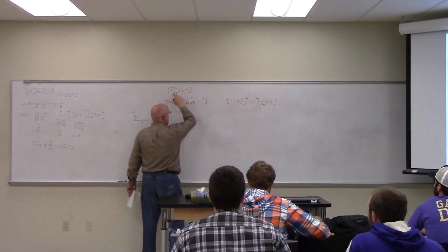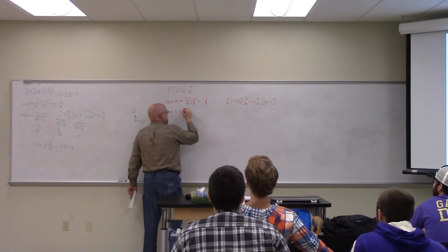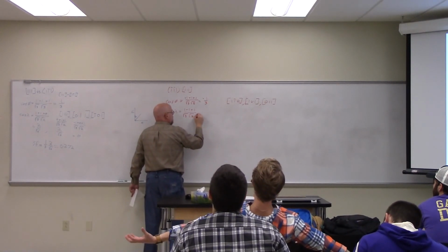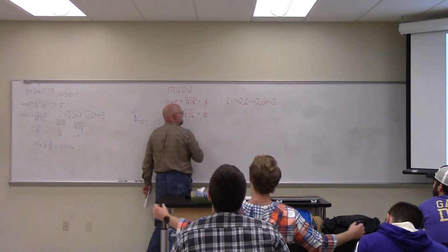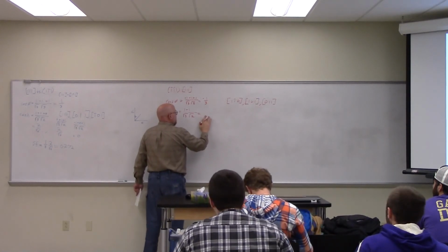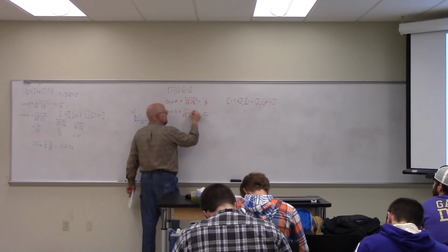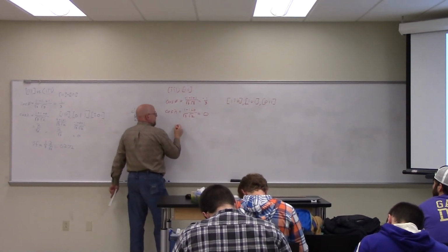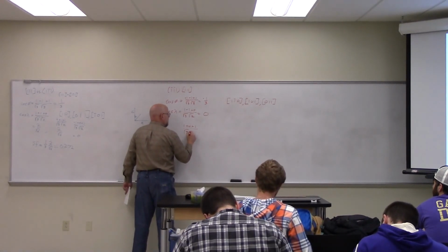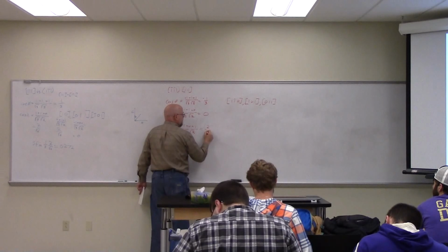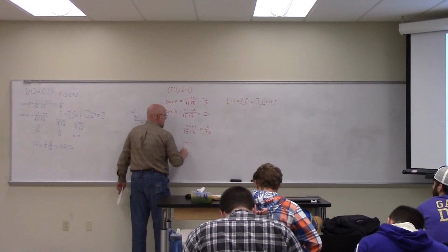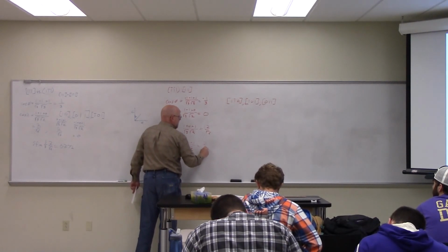The dot product of this with 1, 1, 1 is +1 -1 +1 over square root of 3, square root of 2. So that's equal to 1 over root 6. One of those should be 0. Oh, 0, sorry, yeah, you're right. So that's a 0. So the second one then is 1 plus 0 plus 1 over square root of 3, square root of 2. That gives me 2 over root 6. And the third one is 0 plus 1 plus 1 over the square root of 3, square root of 2, which is equal to 2 over root 6.